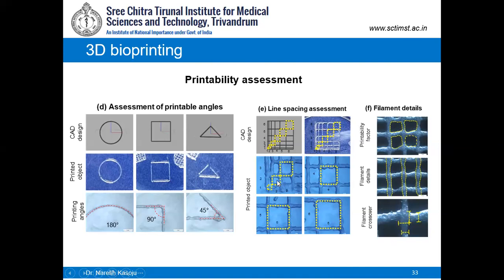And this is the actual print. When you look through the stereo microscope, you would see that this 1 mm by 1 mm gap which I have given is simply collapsed. So this is giving me an indication that the interfilament gap that I have selected here won't work in reality. I may have to go with a minimum of 2 mm by 2 mm gap, so that I can get a construct with a very good porous structure, which is necessary for bioprinting or biological applications, because the exchange of medium and nutrients is very important.